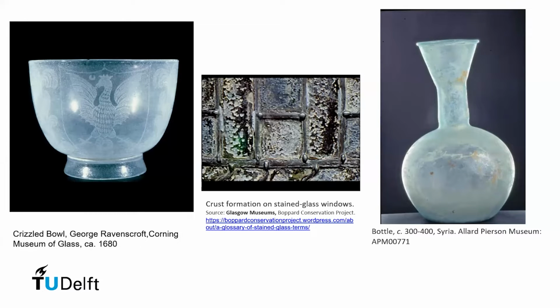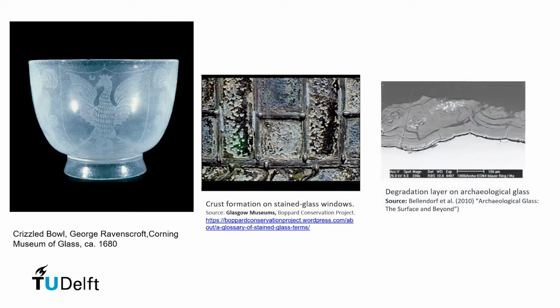For stained glass, the typical degradation process is the formation of what's often referred to as corrosion crusts because of the exposure to harmful pollutants, for example, in the atmosphere. The third group, archaeological glass, has been buried in the ground for such a long period that the degradation has occurred mainly in the ground. And if it's excavated, the glass is usually in pretty stable condition. But what has happened is that a thick layer of laminated glass structures has formed on the surface of the glass, which leads to this characteristic appearance, what they refer to as irisation, so a rainbow effect.